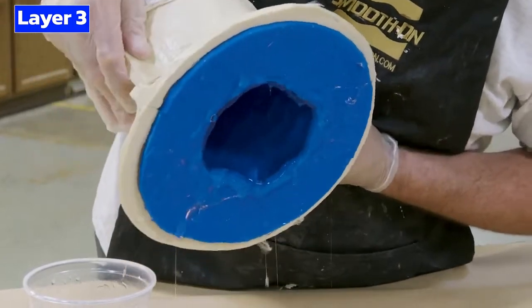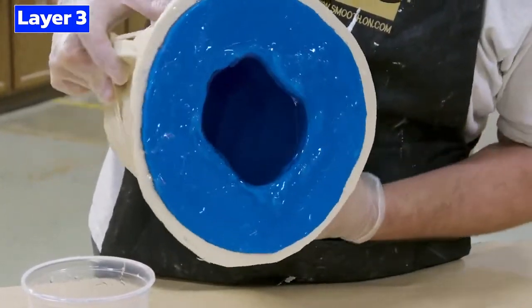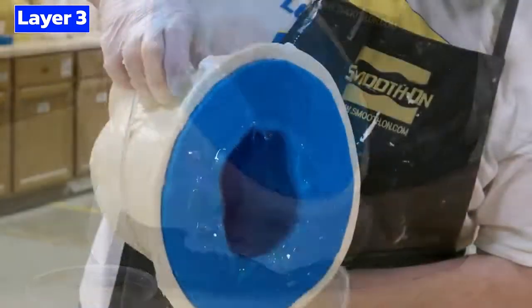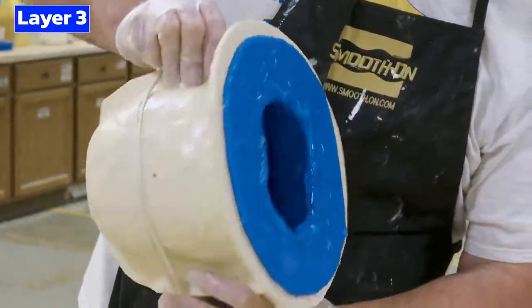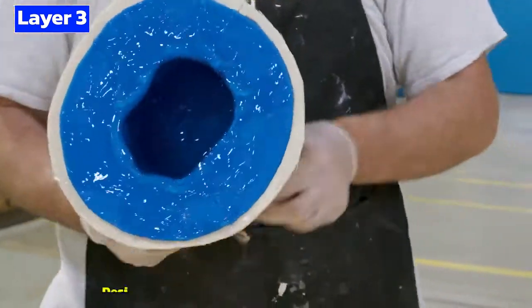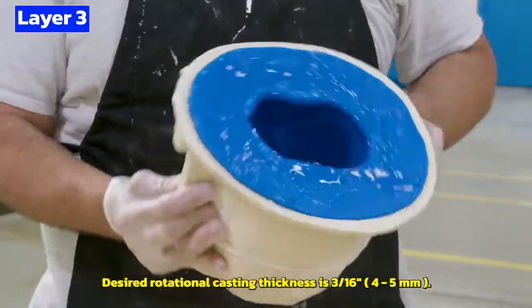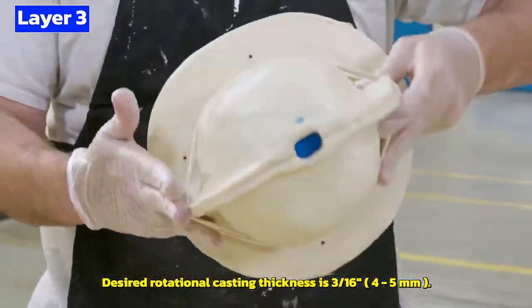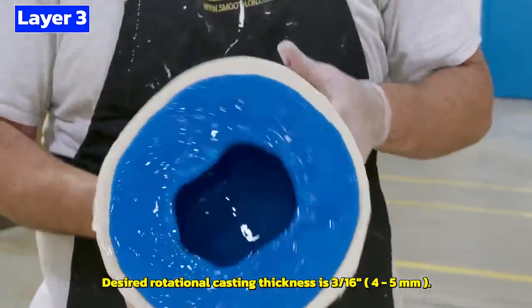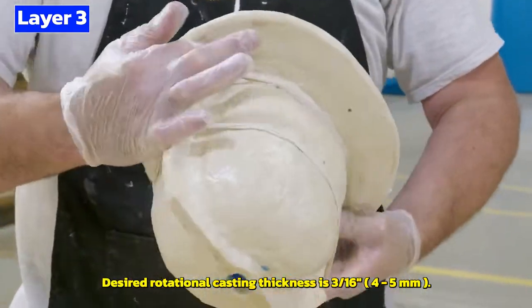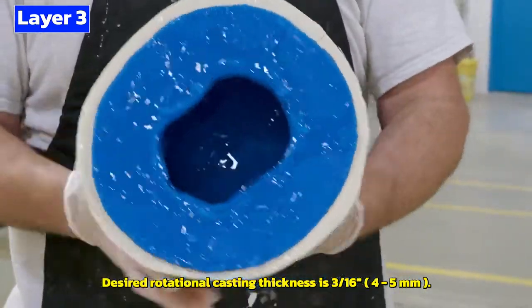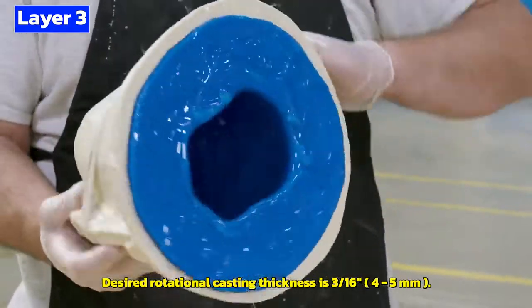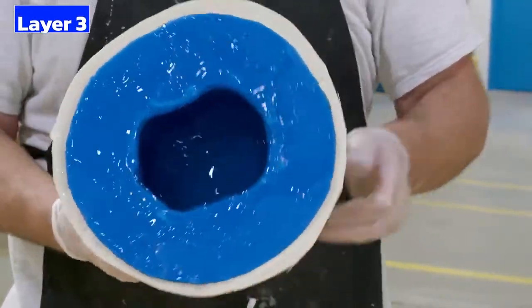Now that the entire inside of the mold is coated with a layer of the resin, we're going to continue spinning the mold in a 360 degree fashion so that we can achieve the ultimate thickness we are looking for in this project, which is about 3/16 of an inch or 4 to 5 millimeters. If you need additional material to achieve that thickness, you can always add additional layers to your casting.